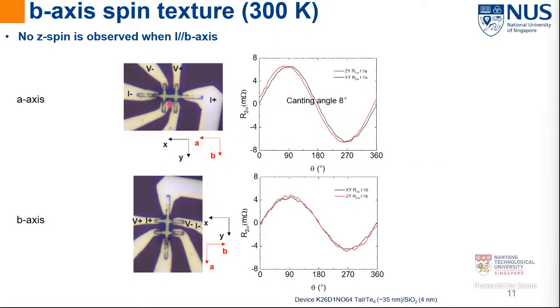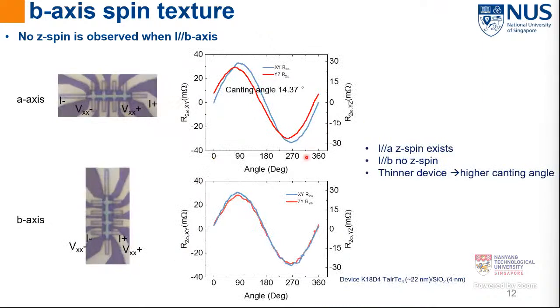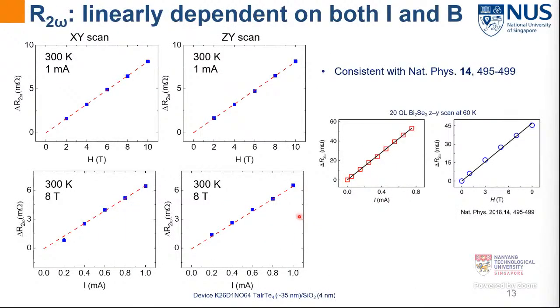If we try another case, where we flow the current along the high symmetry axis, which is also called the B-axis, it can be clearly seen that there is almost no deviation between the XY scan and ZY scan, exactly along 90 degrees, which means that the spin is aligned in the XY plane. And the same experiment has been done in another device, which shows the canting angle along the A-axis, but no Z spin along the B-axis. Besides, by extracting the amplitude of the second harmonic resistance, we find that the amplitude is linearly dependent on both field and current. It's consistent with the published data.